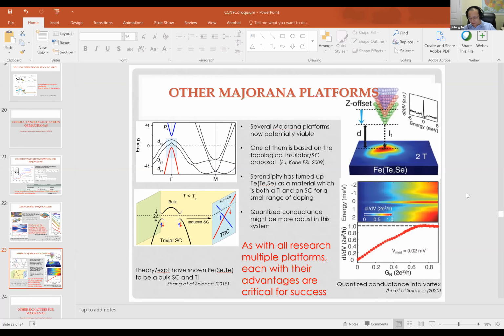Right. I guess they can get rid of it from the surface. Sometimes you can see if there's a big cluster, but what I'm more worried about, if it's a small enough cluster, you can't even tell if there's a few iron clusters. Well, actually, you're right that the surface can be cleaned, but the mechanism we talk about cares about the bulk iron atoms. That will kill the Majorana at the end of the vortex. It's related to that work I did with Ashwin on the relationship of the edge Majorana and bulk superconducting state. Right.